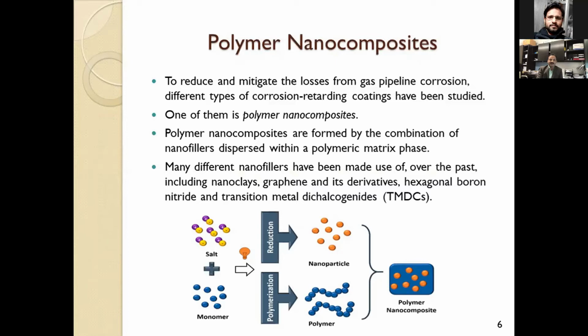Why are polymer nanocomposites such an attractive material for use as corrosion inhibitors within the gas pipelines? That would be a very important question that can come to mind. Well, the one main reason is that it consists of two phases. One is the polymer, and the second is the nanomaterial or the nanofiller. Nanofillers are certain filler particles which have nanometer sized dimensions. At least one of those dimensions is nanometer sized, because of which it has enhanced properties as compared to a bulk material.